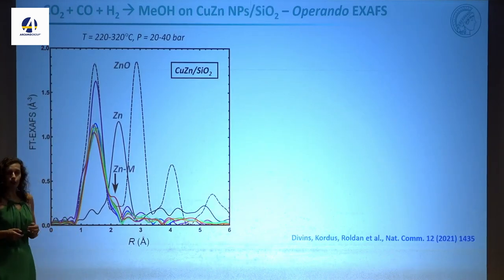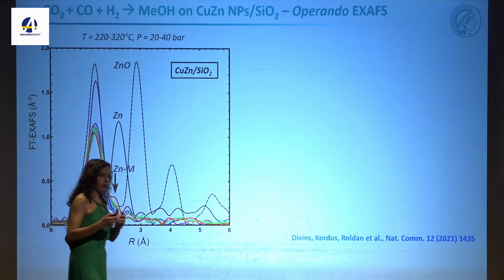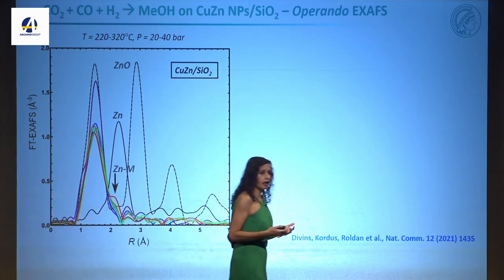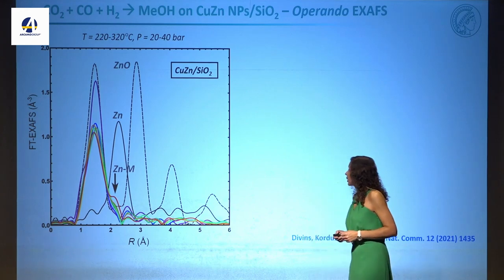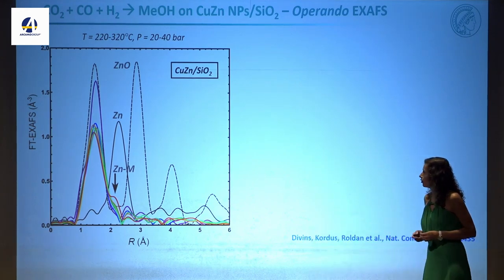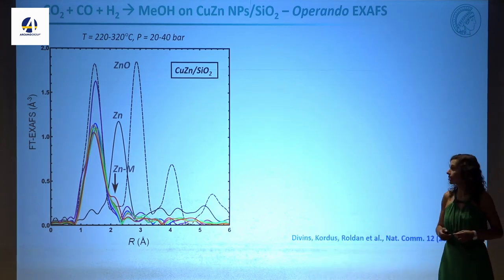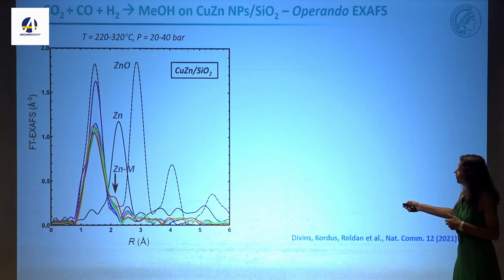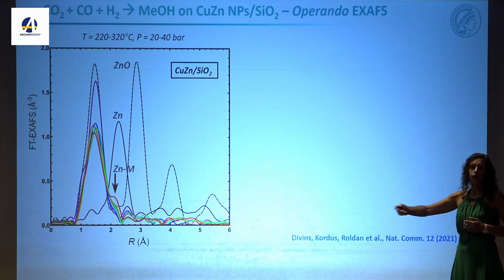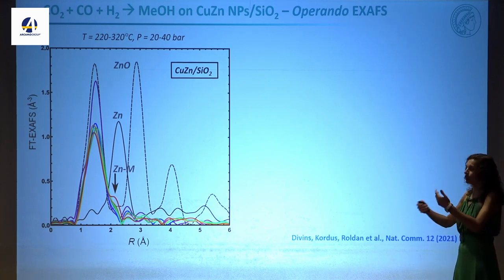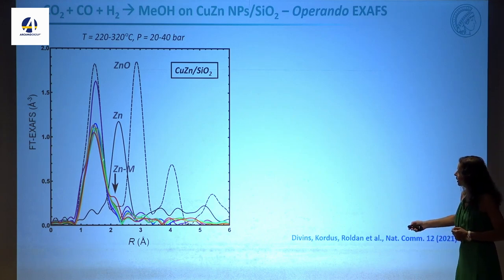And the question in the literature is, are we making brass, and what is the implication of that? Now, because we can follow the zinc signal in high detail, we can see we are making brass. These are Fourier transform X-ray absorption spectroscopy data, EXAFS, and we look at different temperatures, and if you stay at the low temperature for about 24 hours, we make brass. If you go to higher temperature, you can see it much better. And this is the example. This is here zinc oxide.